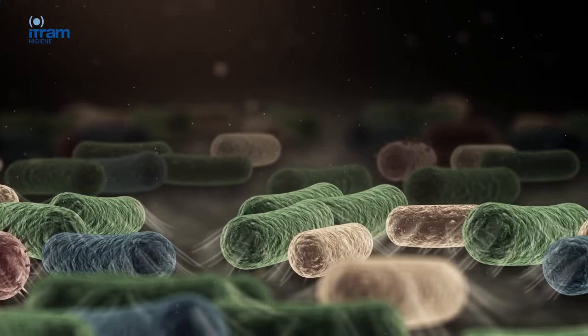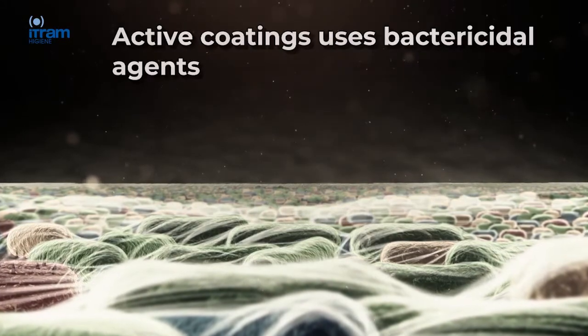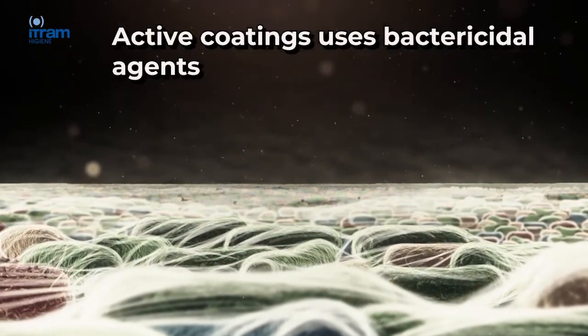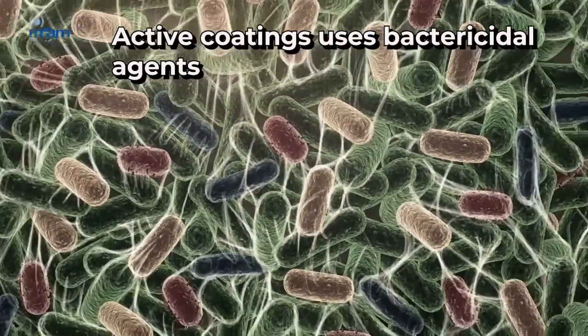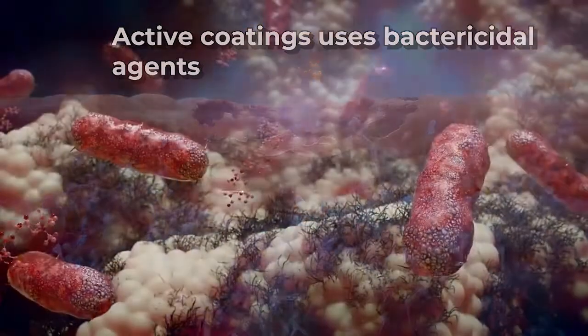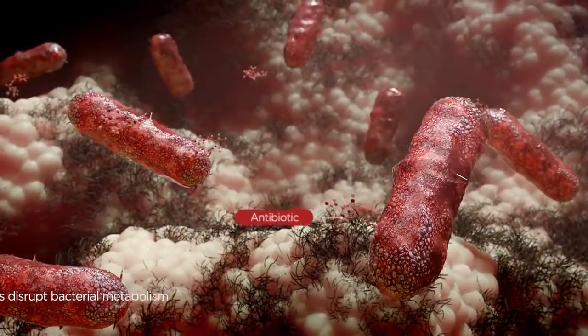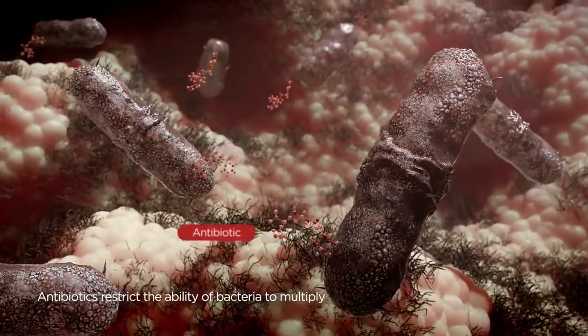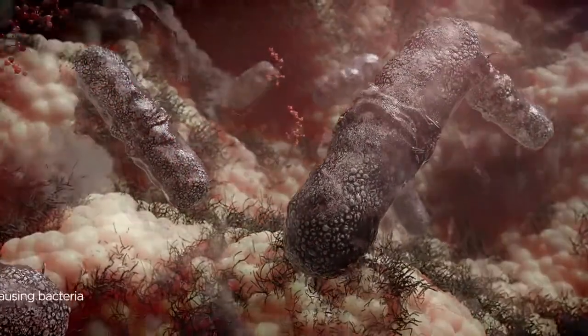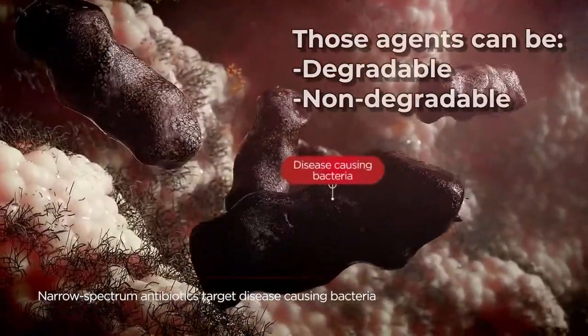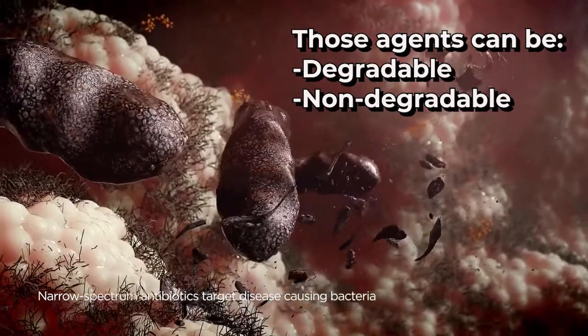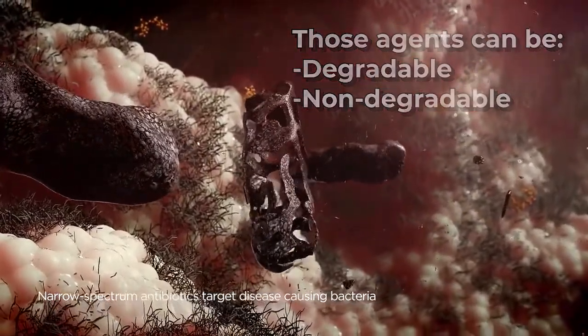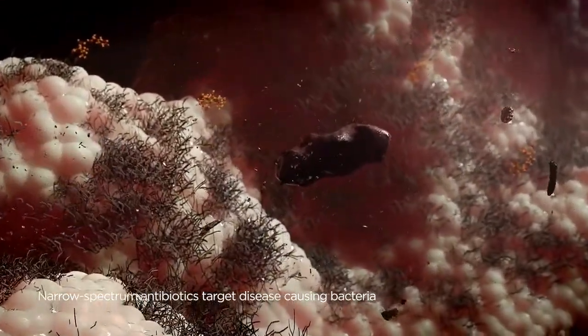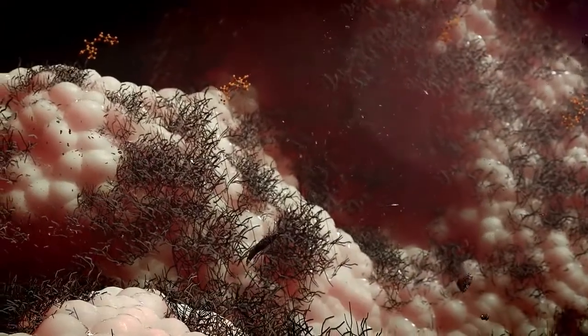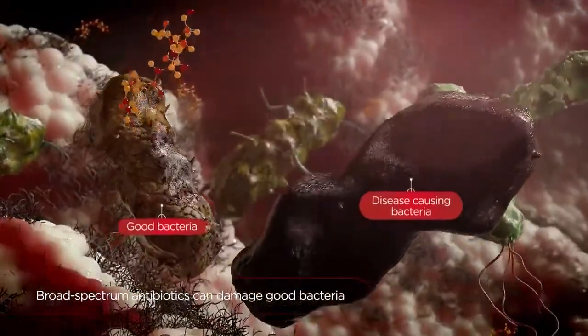On the other hand, active surface modifications are coatings that deliver pharmacologically active pre-incorporated bactericidal agents. For instance, antibiotics, antiseptics, metal ions, or organic molecules are delivered with contact-killing or drug-eluting activity. On the other hand, the pharmacological agents can be degradable or non-degradable. The idea is to interfere with the cell respiration, division, wall formation or bacterial signaling.